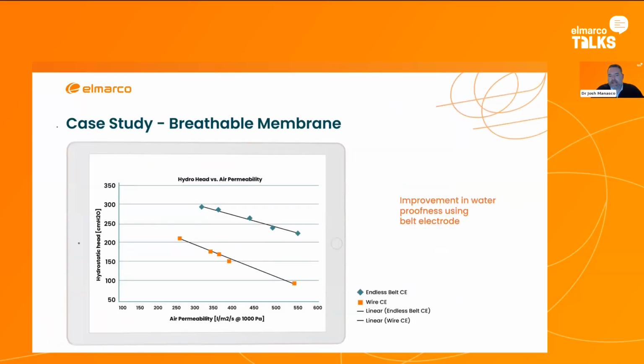And this was in the case where we had a material that we were working on for a customer. We were looking to get a high hydro head, which is waterproofness. You can see that for very similar air permeabilities, we were spinning on the endless belt versus the wire, and we can get even higher hydro heads. We were basing this on uniformity differences at the micro scale, where we were able to make a better waterproof membrane or barrier for this particular combination of fibers and substrate. So it's a case study where we proved out that in this case this gave us superior performance.